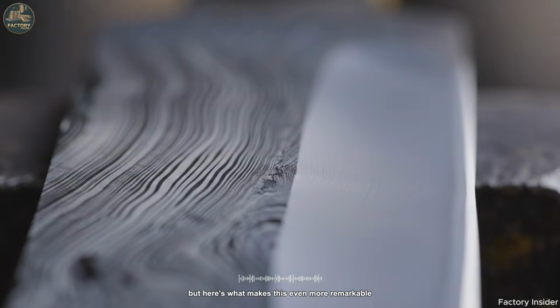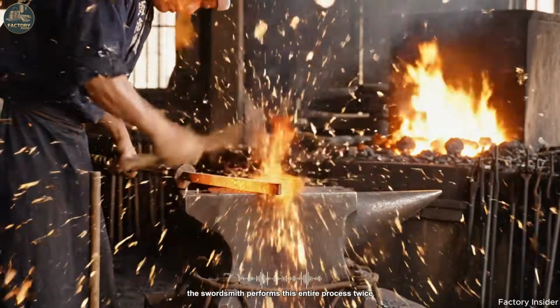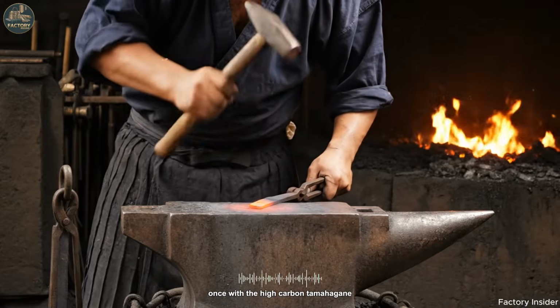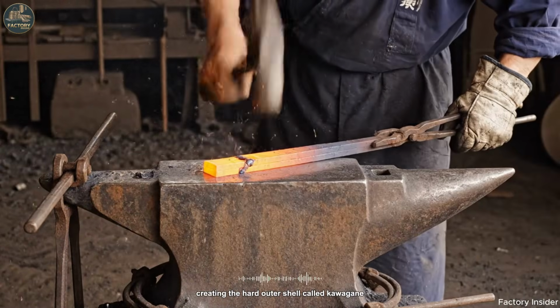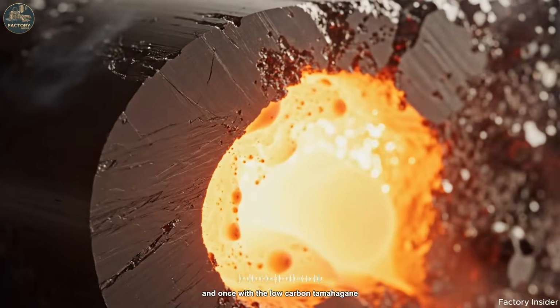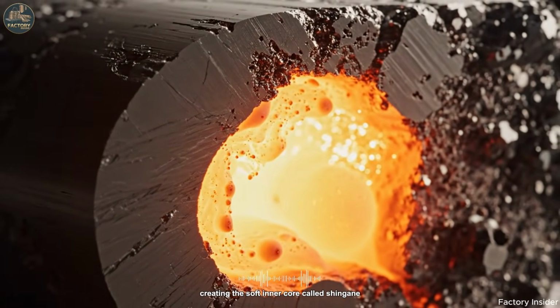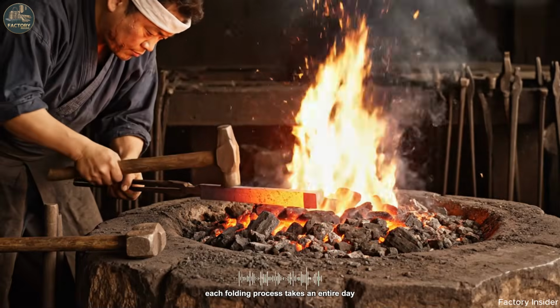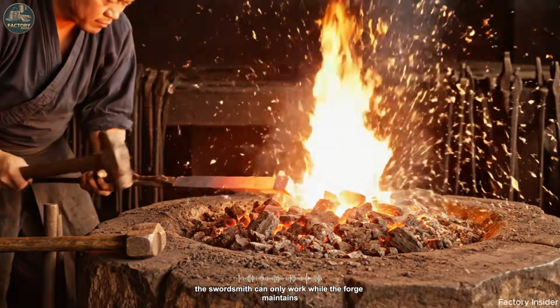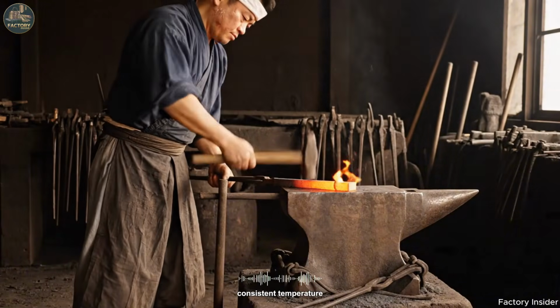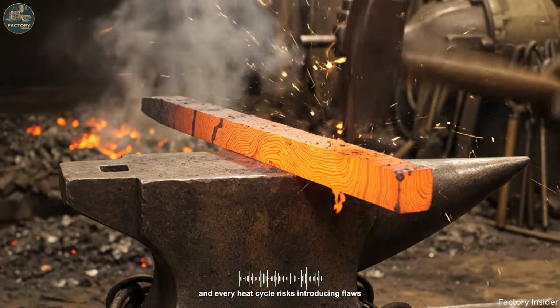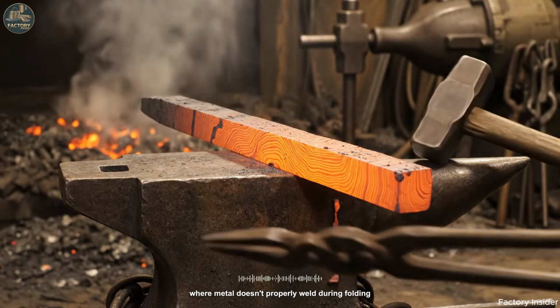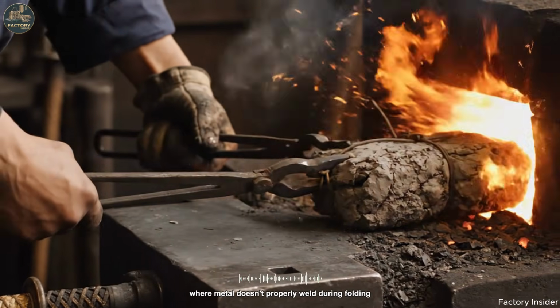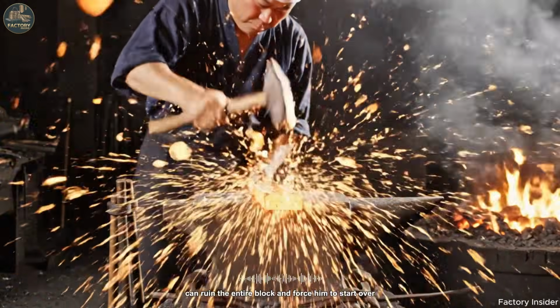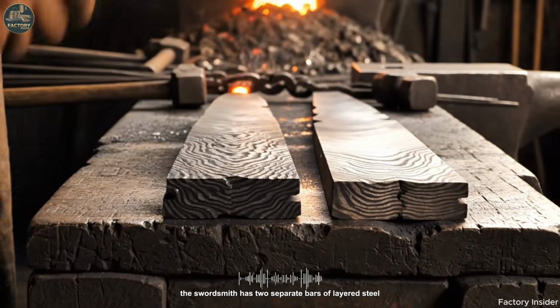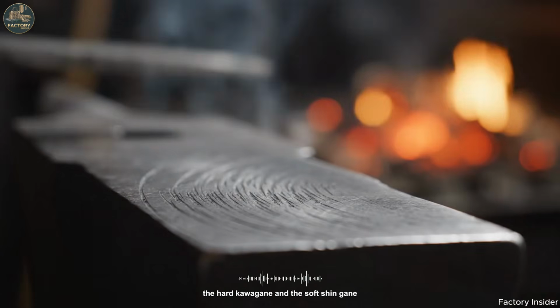But here's what makes this even more remarkable. The swordsmith performs this entire process twice. Once with the high-carbon Tamahagane, creating the hard outer shell called kawagane, and once with the low-carbon Tamahagane, creating the soft inner core called shingane. Each folding process takes an entire day. The swordsmith can only work while the forge maintains consistent temperature, and every heat cycle risks introducing flaws. A single cold shut, where metal doesn't properly weld during folding, can ruin the entire block and force him to start over.